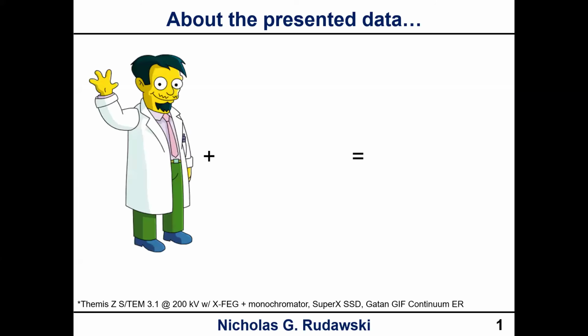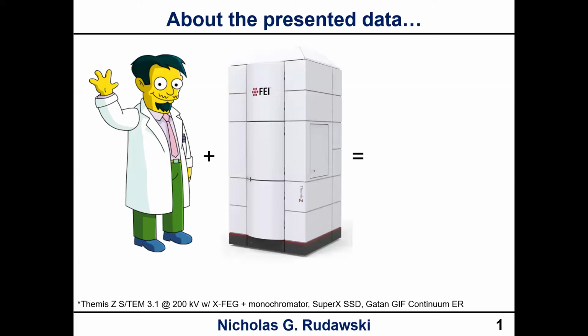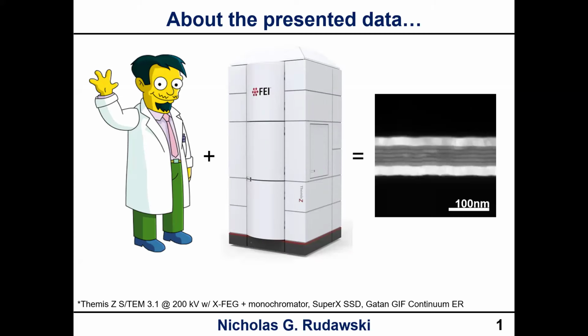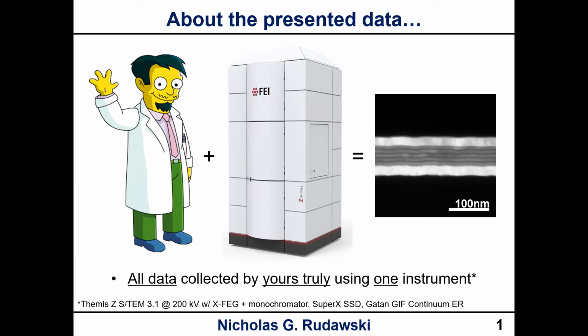So just really quickly about the presented data, right? Here's Dr. Nick from The Simpsons. Here's your microscope. That's a Themis Z in a box. And you put them together and you get STEM data, right? All the data you're seeing here in this presentation was collected by me on one microscope. It's our Themis Z, all done at 200 kV with the X-FEG plus the mono. You have the Super-X SDD and the Gatan GIF Continuum on here.